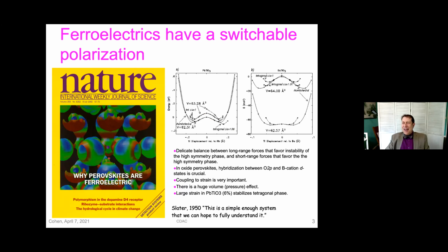And if you did a centrosymmetric crystal, the wave functions are all real. And so all of the tests that had been done didn't find anything wrong because the wave functions were real. But if you had a complex wave function like you do in a polar material, then it made this error. And so once that was fixed, the ferroelectricity came out. So anyway, but things do have to be smooth at this sphere boundary, and we include all the electrons. Yeah.